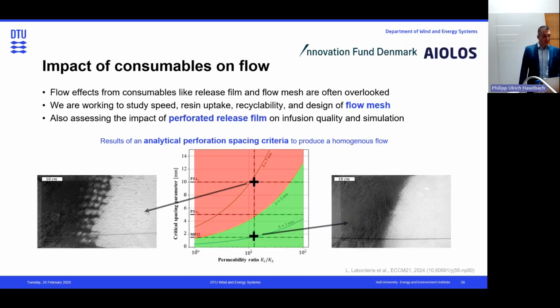Then, impact of consumables on the flow. That's how the mesh looks, and you also put a foil between your fabrics and your mesh, so that you can peel it off later and don't have the grid there. And for example, there you also have the slit foils, and they can have different hole sizes and different distribution of the holes. Depending on how thick your laminate is below, it can have an impact on the resin distribution, and whether you get porosity in the end, dry spots or not, and how everything is filling. One of our PhD students, Lucy, investigated this topic more, and won an award last year for a breakthrough in this characterization, where she came up with an analytical model to predict a selection criteria on the consumables to use.